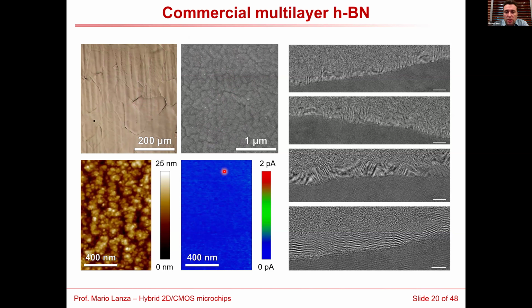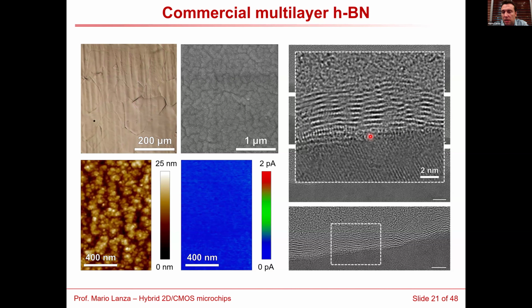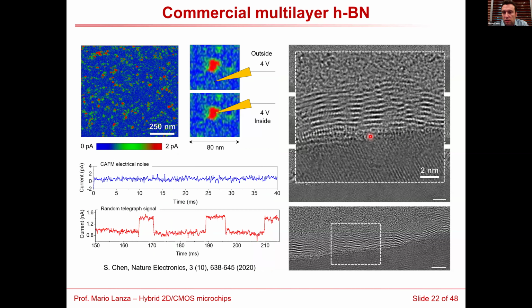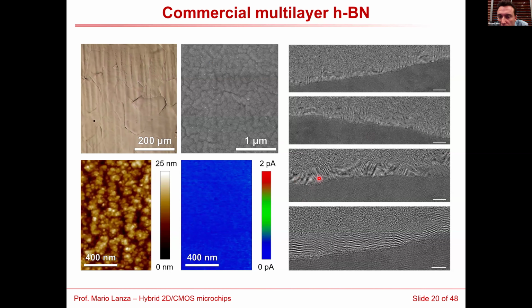However, when we scan the surface of this sample with the conductive AFM, applying a very low voltage, we observe no pinhole, no signal of current, which means that the layer is continuous and it has no pinholes. Actually, you can observe it better in the cross-sectional TEM images. Here you see that the layer is continuous.